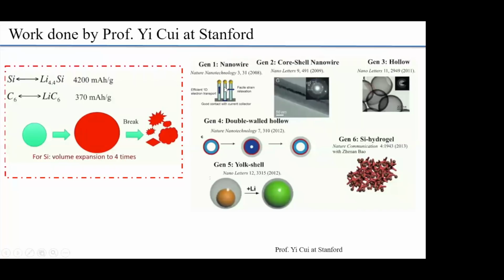They started with nanowires, and then they started making core-shell nanowires and hollow spheres, all in an effort to curtail this volume expansion problem and have a stable solid electrolyte interface. To have just those two: a stable solid electrolyte interface, and then to eliminate this problem of volume change. So then they came up with double-walled hollow structures, where you have a structure like this, and the silicon inside can expand, and the outer grayish circle that you see is the solid electrolyte interface.